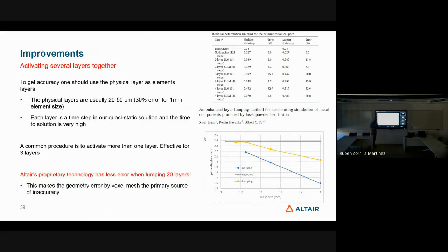But only doing inherent strain is not the whole work, because first of all, you should improve it for performance. Even though this linear solution of the structure is very fast, if you have 10,000 layers, meaning 10,000 time steps, it will need a lot of time. So the question is how we can activate more than one layer together. But if you activate more than one layer, then you have a serious problem, because the discontinuity inherited from the layer by layer powder deposition should be taken into account in some way. We did some study, and there are papers claiming that they can do about 3 layers. In fact, they say that if you go for 3 layers, the error is 11%, and if you go for 4 layers, the error is 52%.